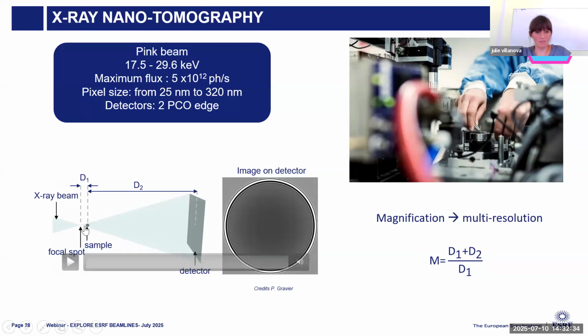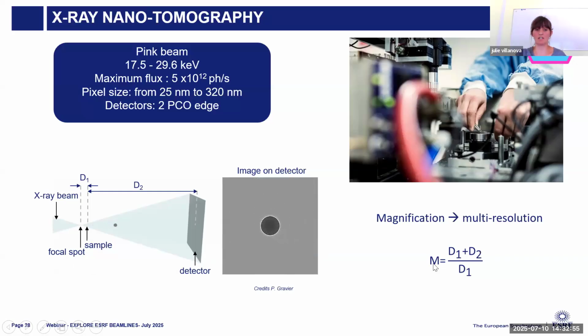So, as I said at the beginning, we use the focus spot as a secondary source, where we put a detector at a fixed distance from this spot, and we are using the cone beam. And this is very practical because, since we are using the cone beam, depending on where we put the sample, we can change the magnification. So it means the pixel size. So we work from 25 nanometers to 320, but also then the field of view.